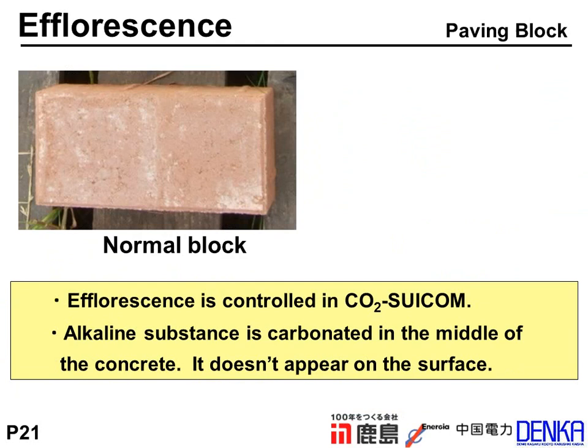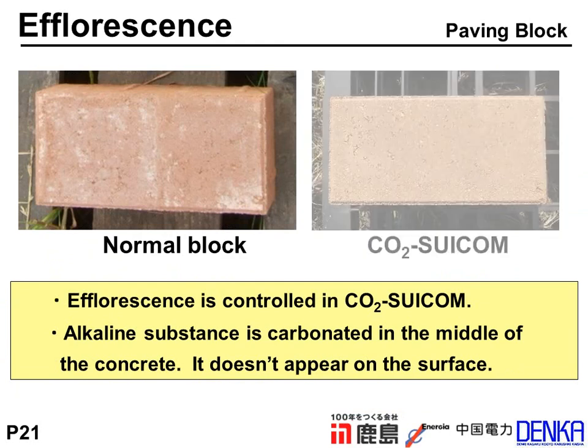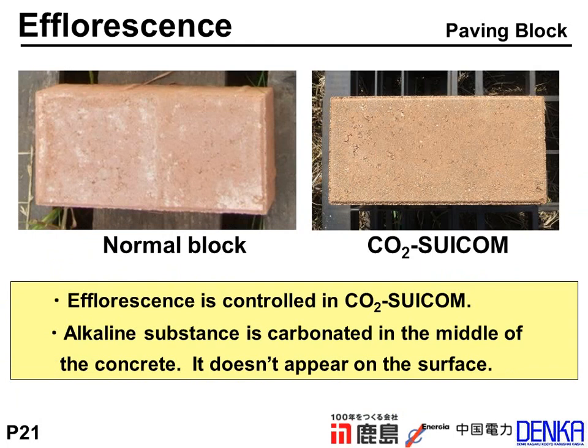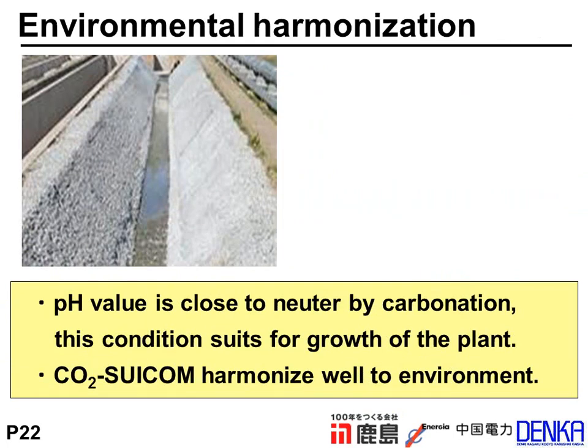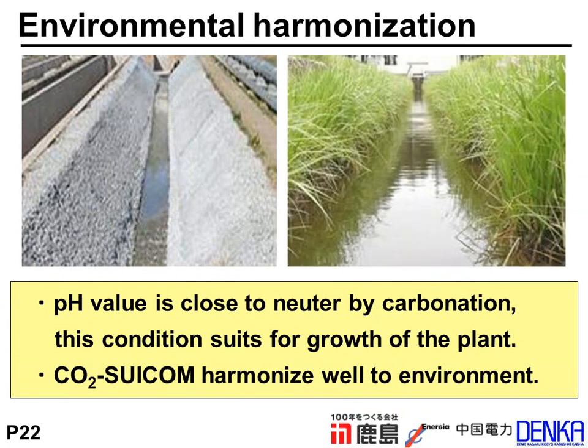And this picture is an example of the efflorescence. You can see the efflorescence on the normal block, like this white substance. On the other hand, efflorescence is controlled in CO2-SUICOM. The alkaline substance is carbonated in the middle of the concrete, so it does not appear on the surface. And the pH value of CO2-SUICOM is close to neutral by carbonation. So this condition suits the growth of plants. CO2-SUICOM harmonizes well with the environment.